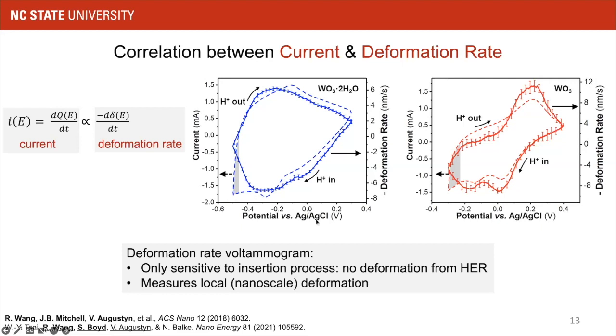And you can see we have extremely close agreement, except in the region where we have the onset of the hydrogen evolution reaction on the electrode surface, which is being measured with the potentiostat, but which does not cause a volume change in the material, and therefore doesn't register on the AFM tip. So we have this really nice technique to measure very locally the deformation of material, and that can be applied to study, for example, the spatial heterogeneity of material deformation across the electrode.